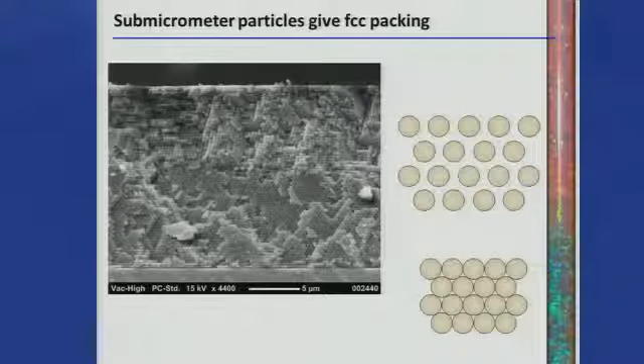And this is my Sandy Asher slide, actually, who's seated right here next to me. So I first heard about colloidal crystals from Sandy Asher. And Sandy's done a lot of beautiful work using polymer beads instead of silica beads. And so this is one, we're now getting better and better at this. This is one we made in our lab with silica. What Sandy does is he uses polymer spheres that are charged, and they are fluid in solution, and so they keep this distance because of electrostatic repulsion, as opposed to ours, which have this hard sphere repulsion. And so I always make the distinction between Sandy Asher colloidal crystals and ours.